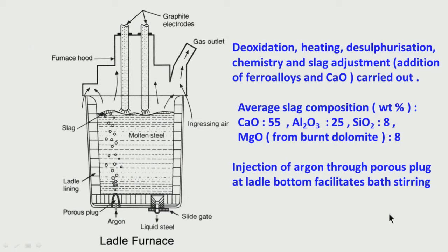We know that we have to tap the liquid steel from BOF, EF, that means from the primary stage, into a ladle. We are taking care that slag from the primary stage should not come, it should be restricted, preferably should not come, it has to be controlled within a very small amount, because it has FeO, MnO, P2O5, all these oxides are undesirable in the ladle.